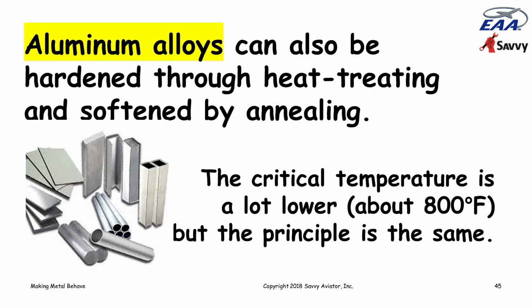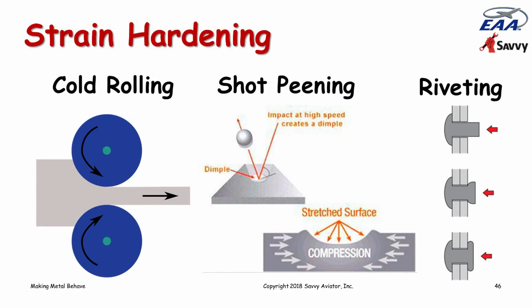In addition to heat treating, there are some other things that we can do to change the hardness of metal. We can do something called strain hardening. Basically, strain hardening means that if we take metal and we forcibly compress it, it becomes harder. And there are various processes for doing this. We can use cold rolling, which is one of the processes that's used in making 2024 T3 aluminum. We can do something called shot peening, where we shoot little hard metal pellets at the surface and create a whole bunch of little tiny dimples.